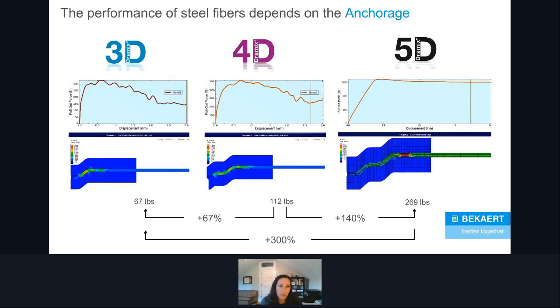So these screen grabs show a single fiber anchored in what's shown as blue concrete, and where the kind of green and colored portion of that anchorage is where that fiber has pulled out at the end of this low displacement test. So you can see that in this particular case that it's pulled out away from the edge of its initial anchorage. So the slow controlled deformation and flattening of that end hook is where the ductility of that SFRC is going to be coming from with a 3D or 4D fiber.